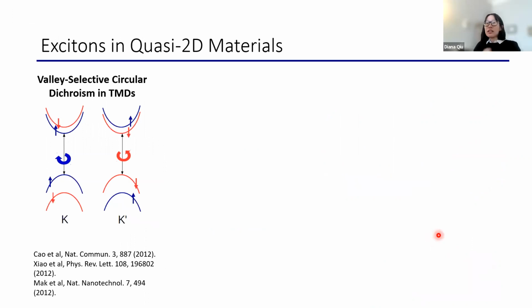Yes. So essentially, the A and B excitons are coming from the spin-orbit coupling. The A exciton comes from the lowest energy transition, between, let's say, the blue bands, and the B exciton is the spin-orbit split transition. The A exciton is doubly degenerate, so it contains both the blue band to blue band transition at K and the red band to red band transition at K prime.